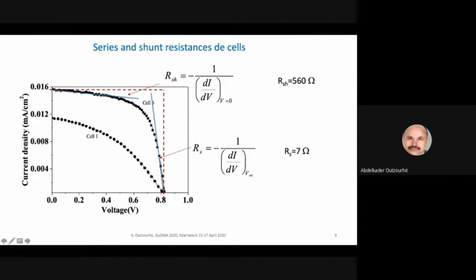The shunt resistance, on the other hand, is due to current leakage across the cell, and this value is rather small. Normally it should be higher than that. This explains why the fill factor, which is the ratio of the area under the curve of the cell to the area of this rectangle, determined by the short circuit current and the open circuit voltage, is smaller than the reported values for the record efficiency solar cells.